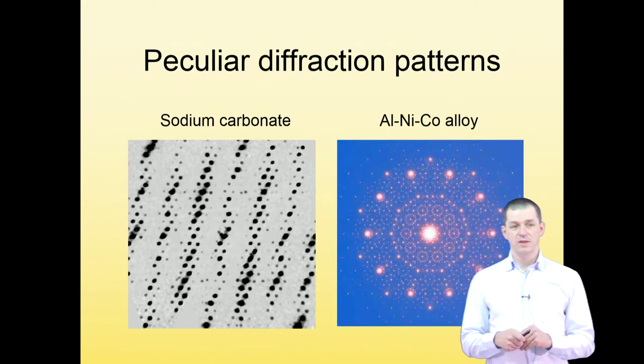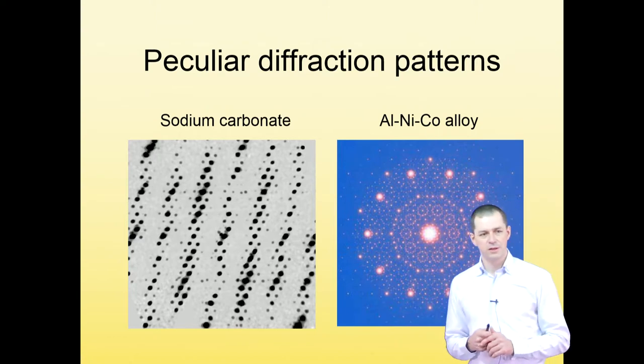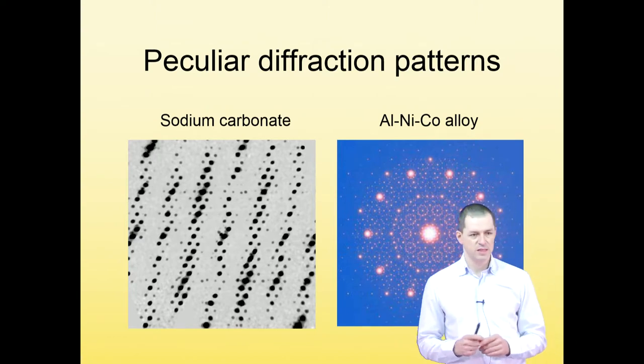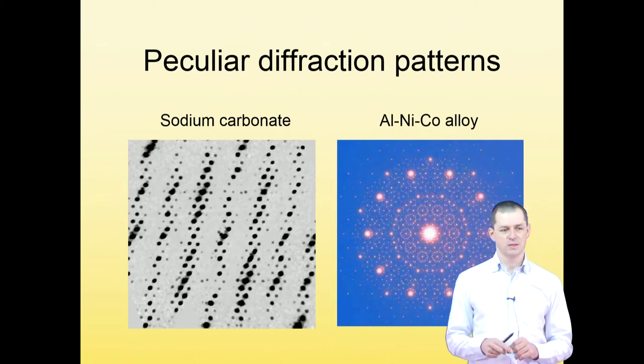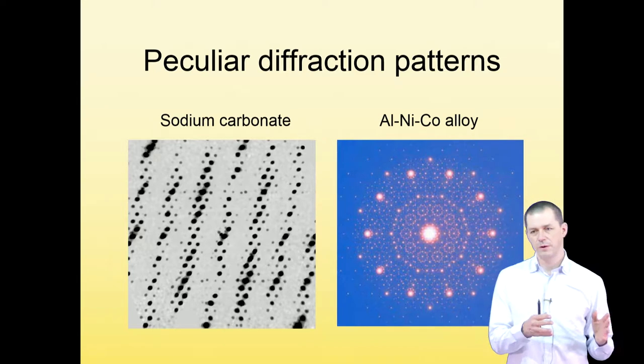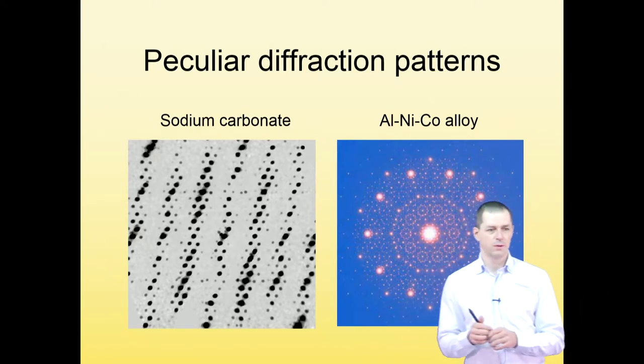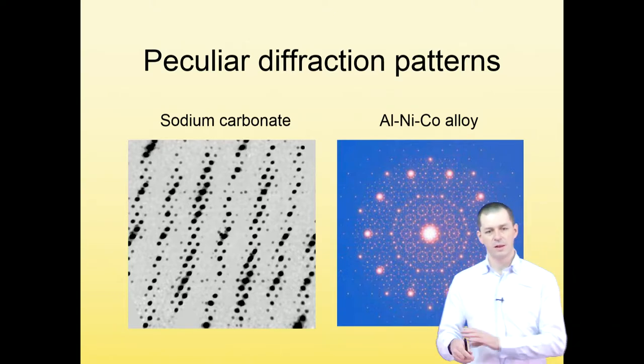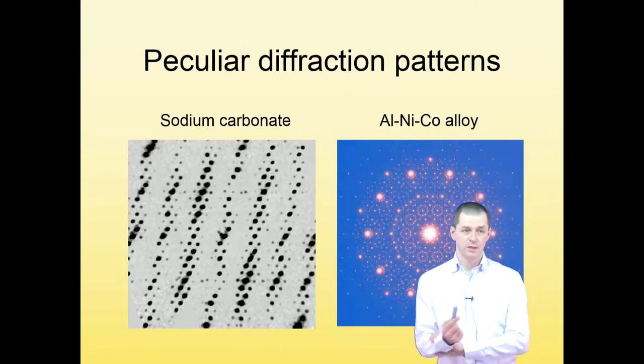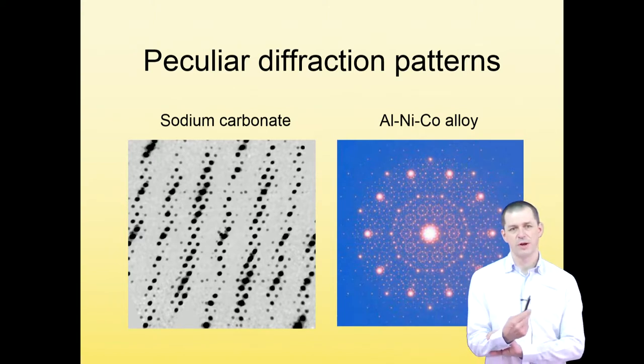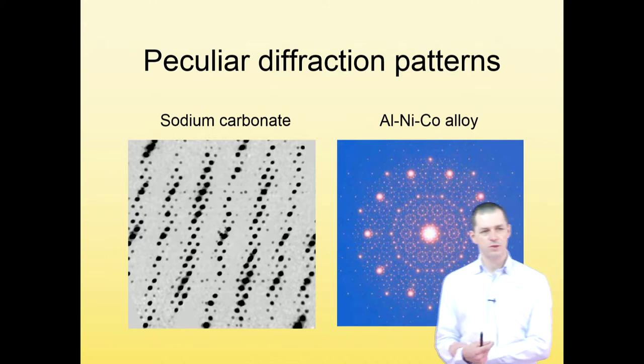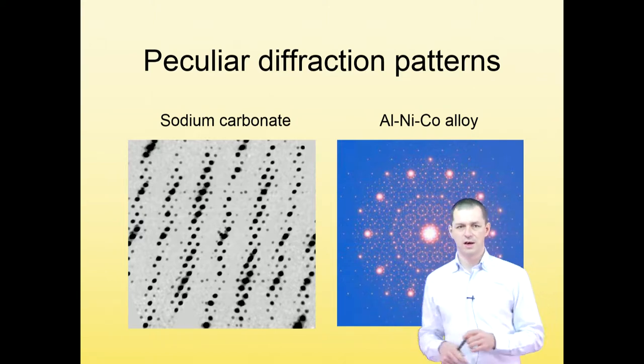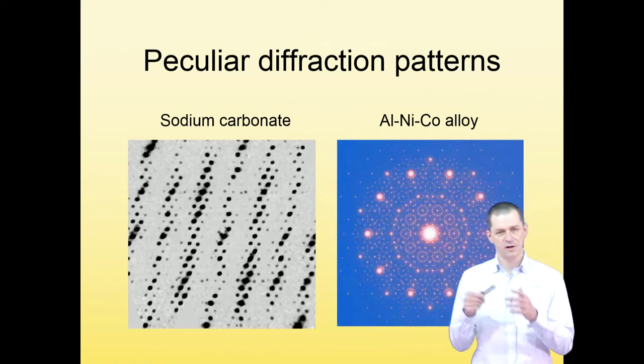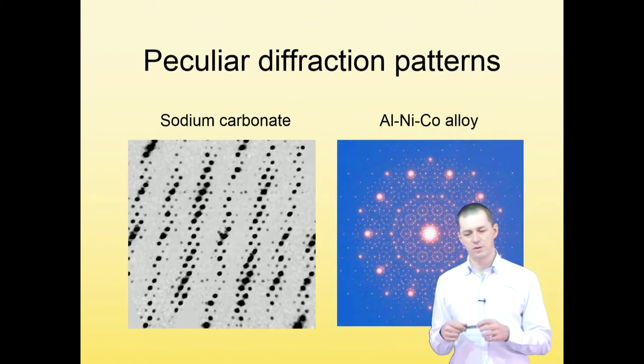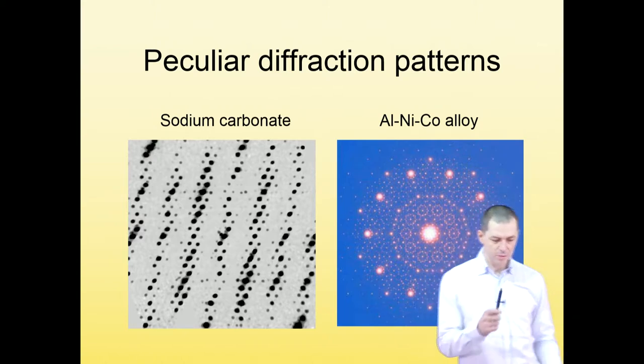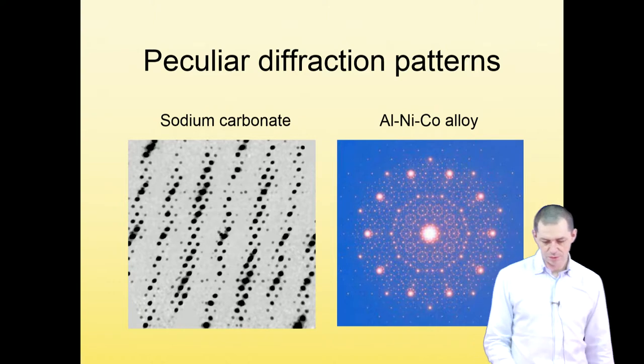However, relatively soon, people started seeing diffraction patterns that were not really matching this assumption. Because a 3D periodic crystal gives a diffraction pattern that can be indexed on a reciprocal lattice with three dimensions. And soon people started seeing diffraction patterns which were not really indexable with three integers, but it took quite a long time before somebody really started thinking about it and developed a way to consistently describe that. But here you see an example of two such strange patterns.